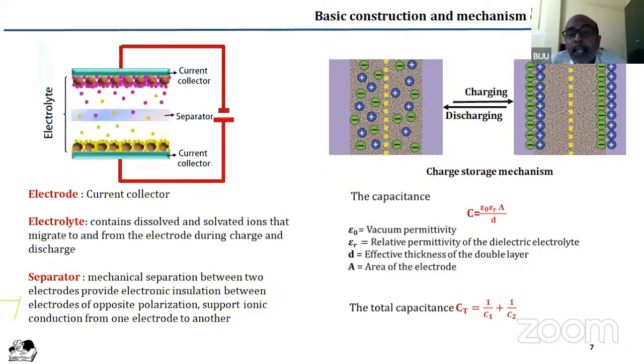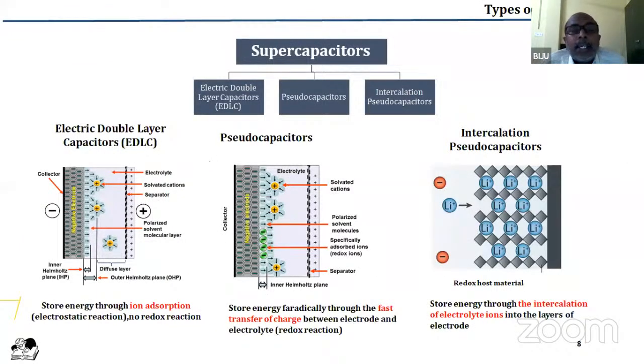Now, here the energy is stored by different energy storage mechanisms, and the three major mechanisms that we have to discuss are the electric double layer mechanism, the pseudo-capacitor mechanism, and intercalation pseudo-capacitors. The first one is the most conventional supercapacitor, where the energy is stored between the electrolyte and an active material. When you apply a positive charge to an electrode, the anions of the electrolyte will form a very thin layer very close to the electrode material, and if your electrode material has very high surface area, a double layer is produced where the active material contains positive charges and the electrolyte layer contains negative charges, and they are separated by a very small distance. This is what is called a double layer.